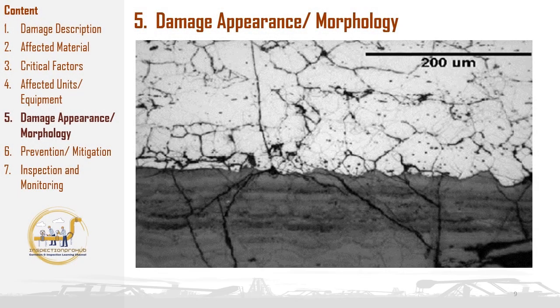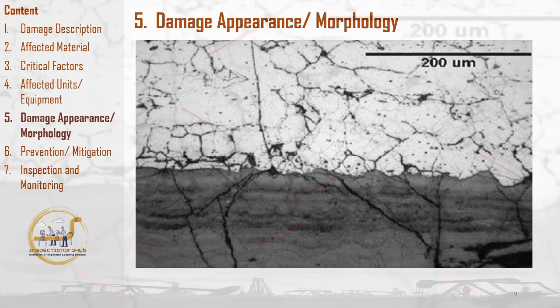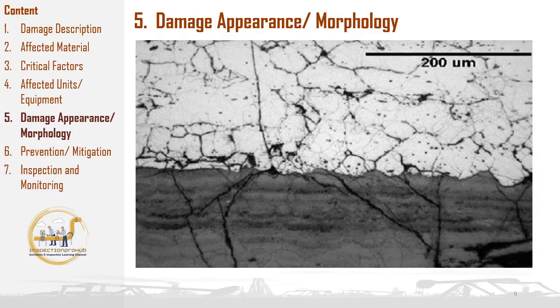This image showcases a sample of a material exhibiting severe embrittlement, as evidenced by the presence of intergranular cracks visible in its microstructure. These intergranular cracks occur along the grain boundaries of the material, indicating a weakening of the bonds between the grains rather than within the grains themselves. This type of cracking is a characteristic feature of embrittlement, which significantly reduces the material's ductility and fracture toughness.